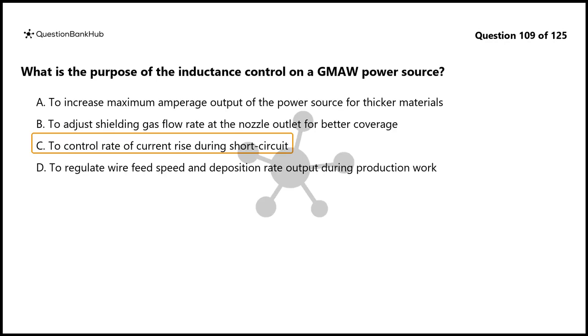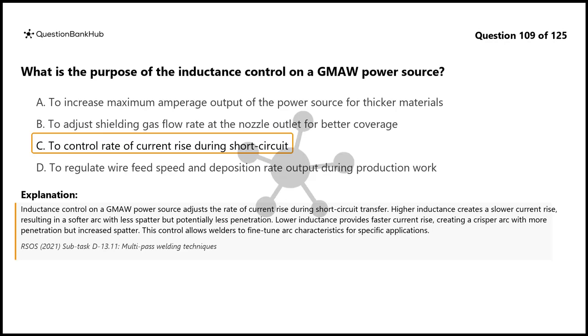The correct answer is C. To control rate of current rise during short circuit. Inductance control on a GMAW power source adjusts the rate of current rise during short circuit transfer. Higher inductance creates a slower current rise, resulting in a softer arc with less spatter but potentially less penetration. Lower inductance provides faster current rise, creating a crisper arc with more penetration but increased spatter. This control allows welders to fine-tune arc characteristics for specific applications.